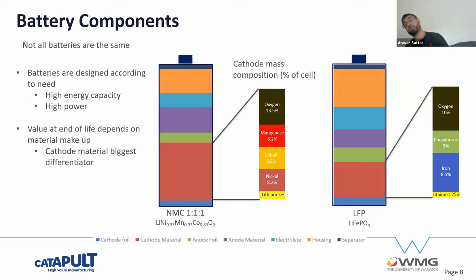Okay, now, of course, not all batteries are the same. So when it comes to recycling, the value in the material is really important, and the value is determined by the metals at the moment. And so batteries themselves are designed according to the need. Some batteries are high power batteries, such as the LFP, and some have high energy capacity, such as the NMC. And if we look at the composition of the battery, we can see that about 10 to 12 or 13% of a battery, depending on how much cathode material is in there, is actually oxygen. So if we go back to that 70% recycling figure, and you think 10% of a battery is made up of oxygen, then it makes that 70% figure very difficult to achieve. And as I explain a bit more, you'll see that it's actually very difficult to achieve.